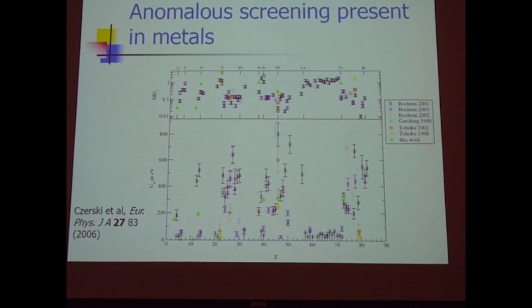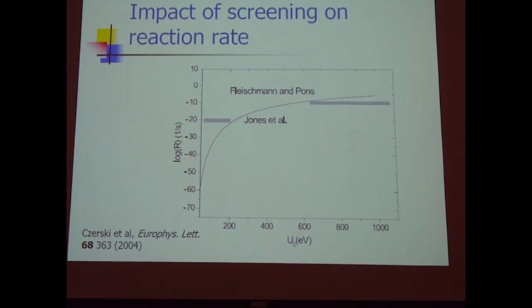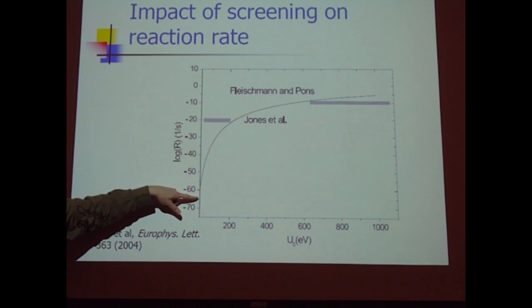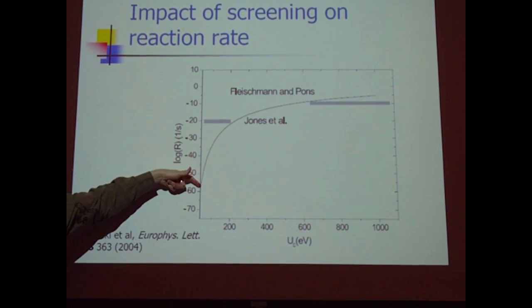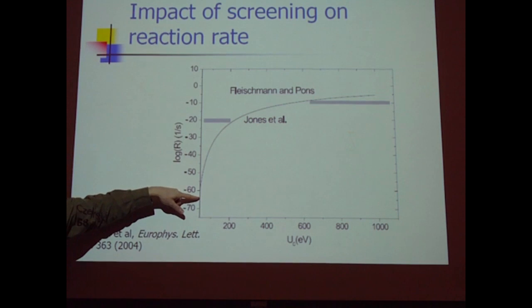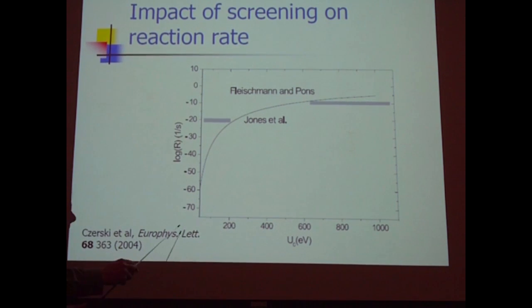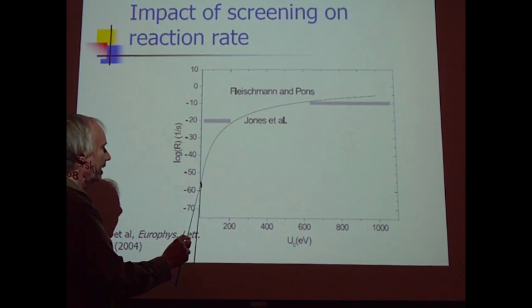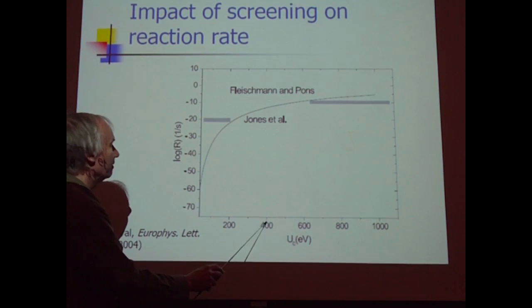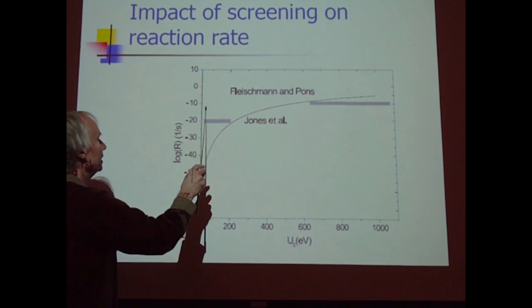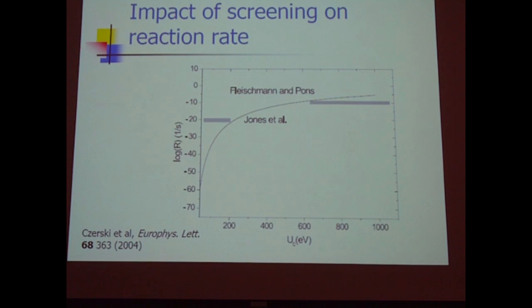So screening occurs. It's a big effect. The screening impacts the incoherent fusion rate. So these curves are well known. If you have screening for the molecule, the calculated rate is somewhere right about here. So this curve, which looks like it's hitting the line here, you should imagine it goes all the way down to about here. Now, if you have a screening energy of, say, 400 volts, then your incoherent reaction rate goes from 10 to the minus 65 up to, I don't know, 10 to the minus 10th or 13th or 14th or something. So that's good for like 50 orders of magnitude.